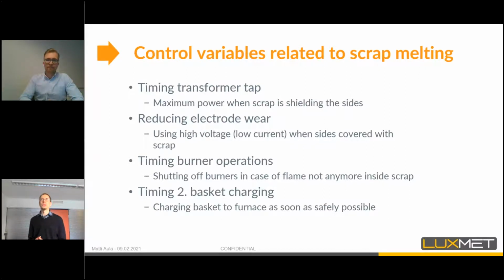Yeah, this information about the scrap melting can be used in many ways, just like we were discussing in the beginning about the furnace. So, for example, when the scrap melts, we can optimize the timing of the voltage taps. So when the scrap melts, we can reduce the taps. On the other hand, we can also time the burners and injectors based on the scrap melting. Like Professor Fabritius mentioned, these burners should be operated only when there's solid scrap there. So if the scrap starts to melt and the burners are not burning inside the scrap, the efficiency of the burners will degrade highly. So you want to be shutting down the burners when the scrap starts to melt, or it's near the end.